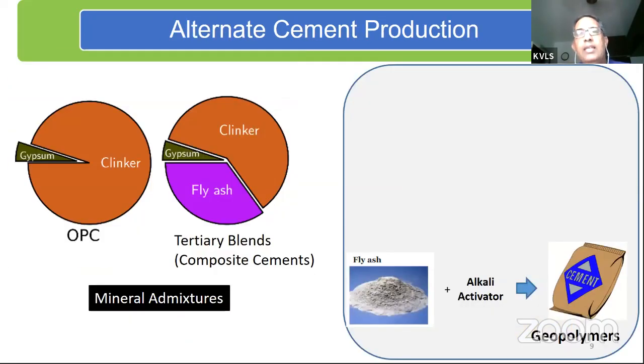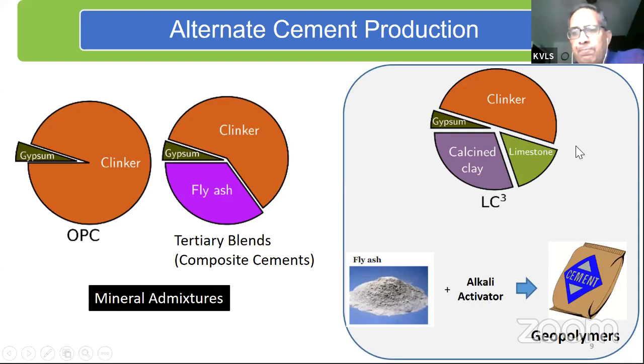Now, there are other cements that are being looked at. We are looking at alternate cements that are coming in the market. One of the cements that is already being produced commercially goes by the name LC3. This has a lower clinker factor; we are reducing the clinker factor quite a bit, down to 50%. We basically use calcined clay, and the clay that goes in here is poor grade clay. This is not clay used for agricultural purposes, but clay that is typically found as mine overburden. Using these materials, we are able to produce cements which have much lower environmental impact.